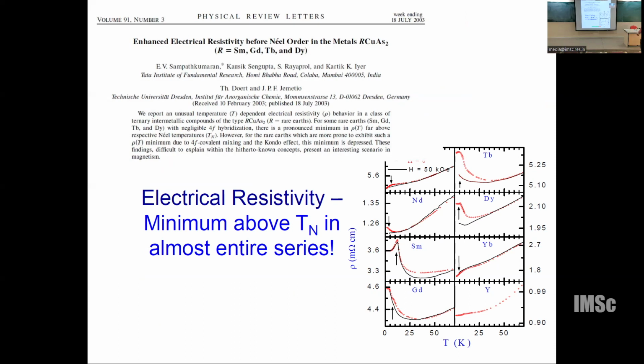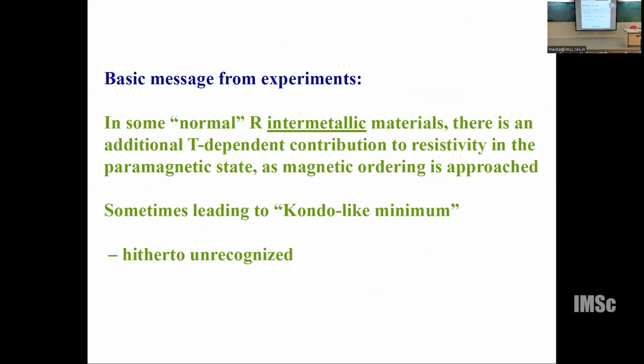Only thing is, people have not studied it very thoroughly. On the one hand, it behaves like a localized moment, on the other hand, Kondo-like, but it is not a Kondo effect. It took tens of decades. The basic message I was trying to propose is that in these rare earth metallic compounds, there is an additional temperature-dependent contribution to resistivity in the paramagnetic state as the magnetic ordering is approached. The scattering contribution keeps increasing as you approach long-range magnetic order, sometimes leading to a Kondo-like minimum. These were not realized in the literature.